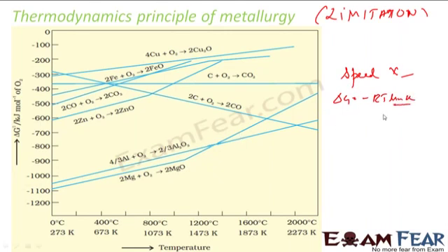But this formula assumes that my reaction is in equilibrium, because this formula is used normally in case of equilibrium, because you get this equilibrium constant, but the reaction may not be in equilibrium. So this may not be a 100% correct figure. Two limitations: one is it doesn't tell anything about the speed, and also to get these values it assumes that the reaction is in equilibrium.